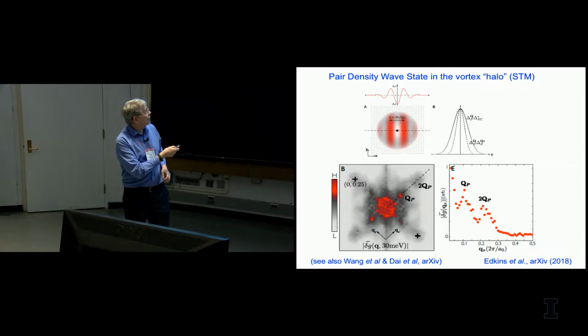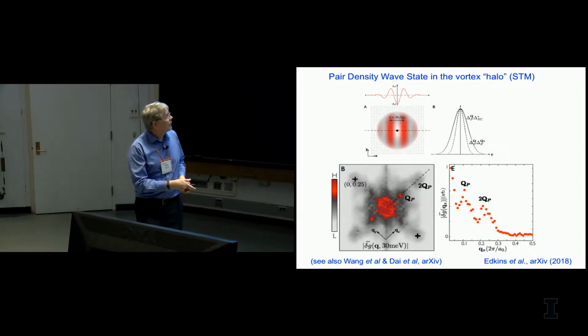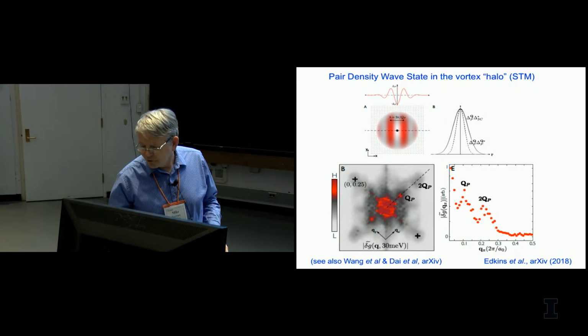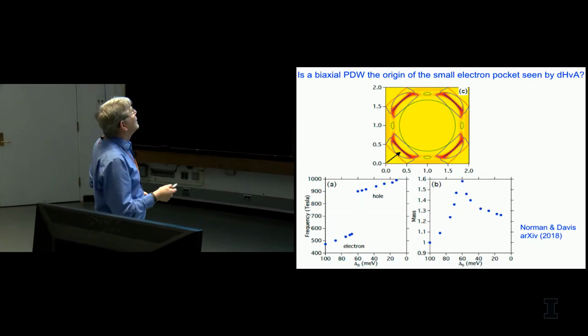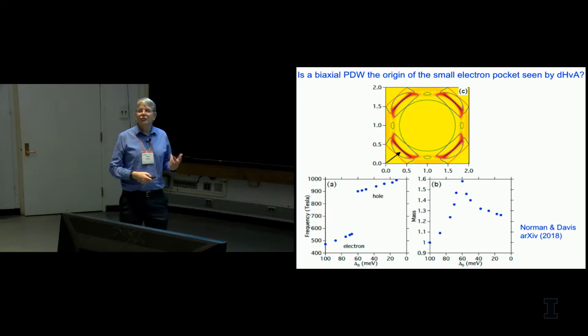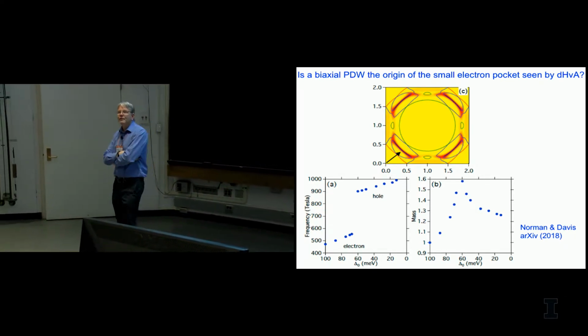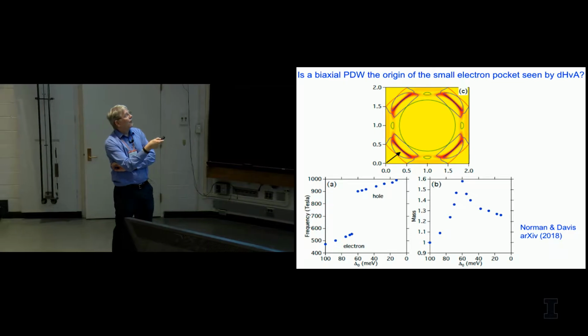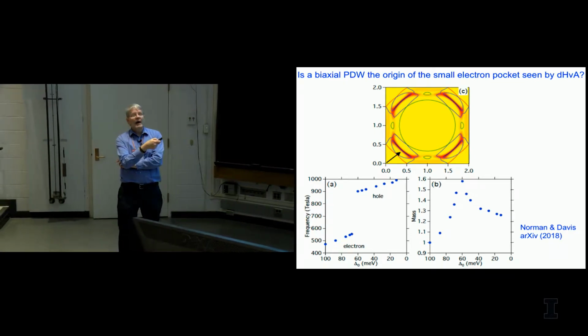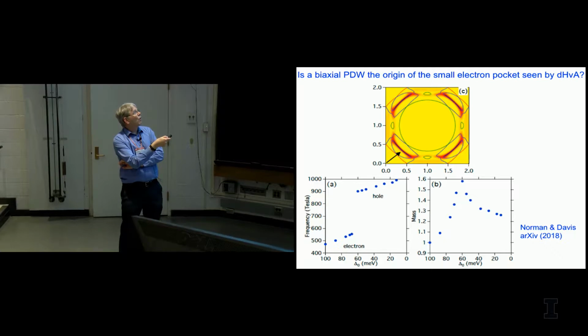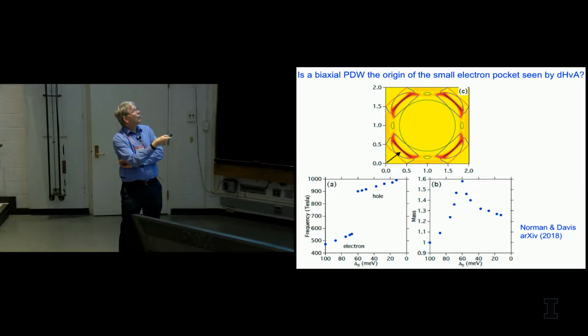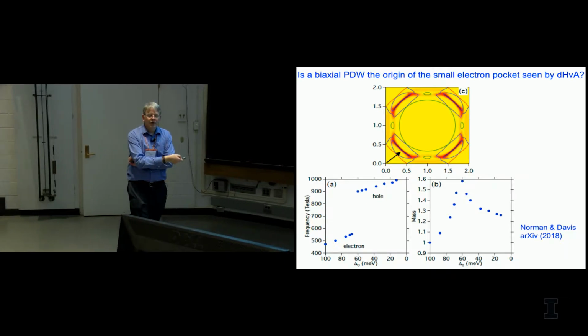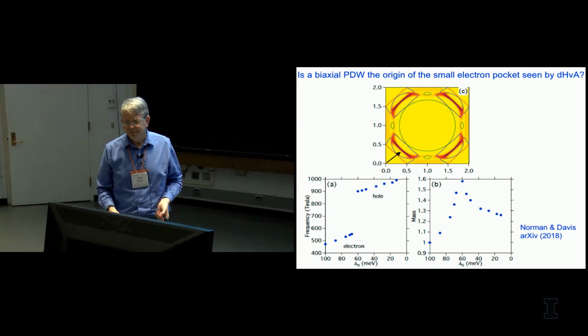And there are two theory papers out on this, one that our chair was involved in. And this led to a recent speculation by Seamus and me that at high fields you see a small electron pocket in these materials despite the fact that it's a hole-doped material. The classic explanation is a biaxial charge density wave state, but we have an alternate scenario based on a biaxial pair density wave state that gives a very different kind of electron pocket, but is still an electron-like pocket that has properties, de Haas-van Alphen frequency and effective mass, that look a lot like the de Haas-van Alphen data.